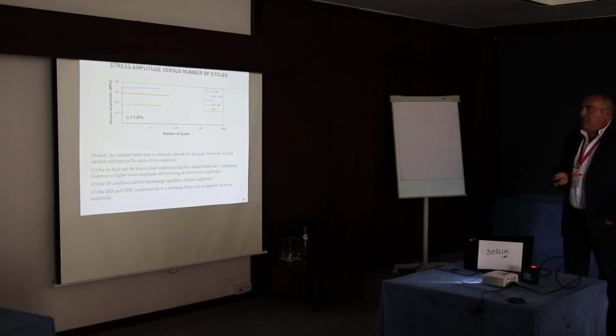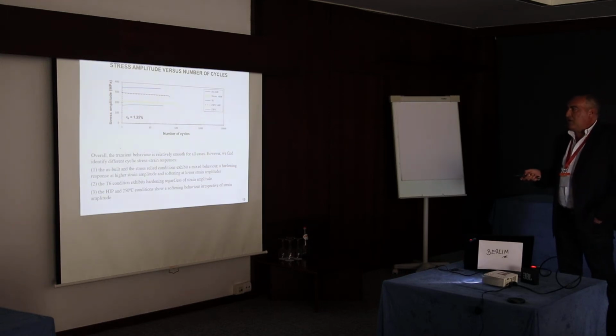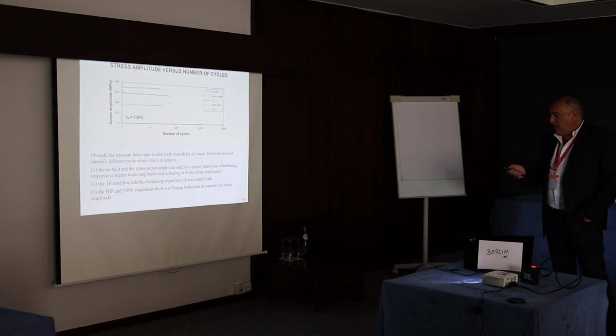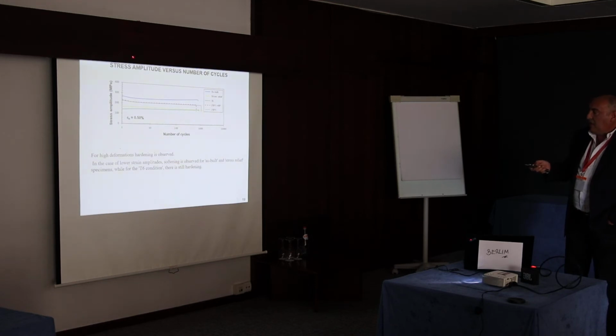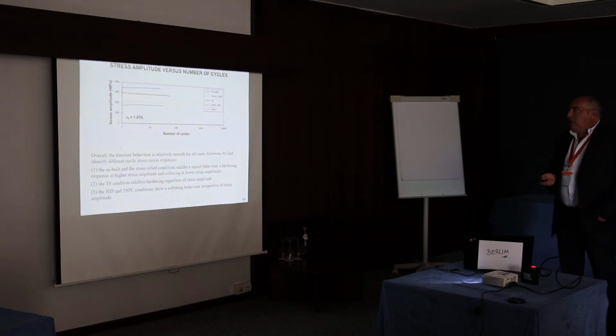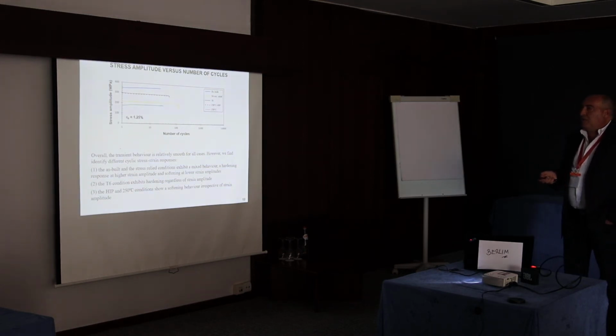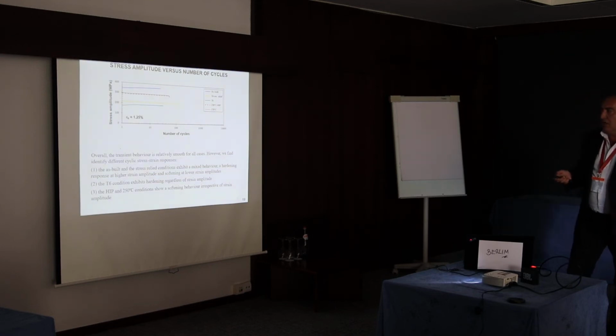The as-built and the stress relief conditions exhibit a mixed behavior, a hardening response at higher strain amplitudes and softening at lower strain amplitudes. We will see in the next graph, because in the next graph we have a lower strain amplitude, this one. You can see there some softening here. And here we see hardening. And the T6 condition exhibits always hardening, and the HIP and the 250 condition show a softening behavior irrespective of strain amplitude. Also, one hardening, the other one always softening.